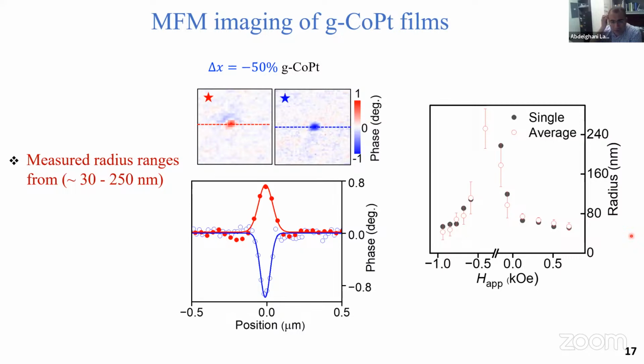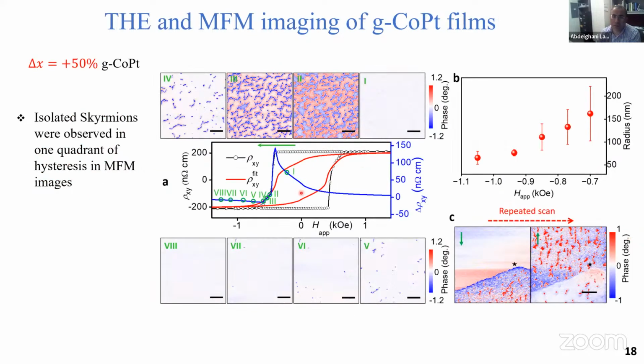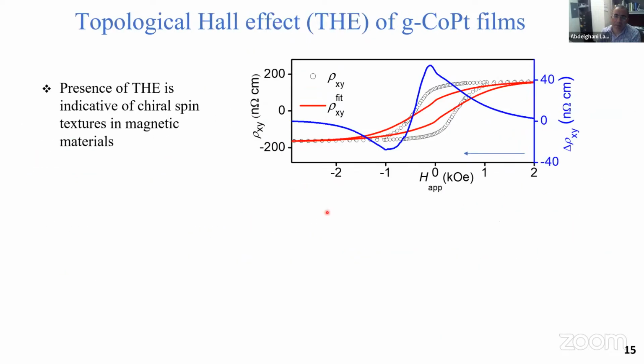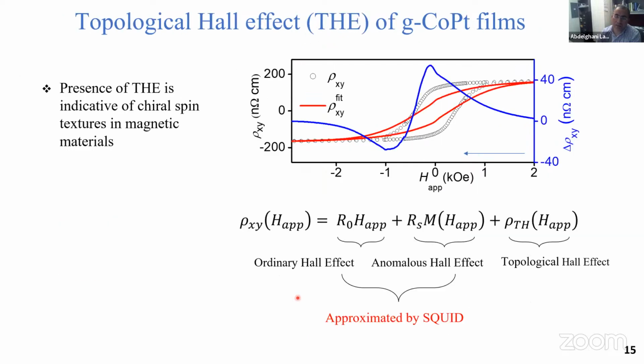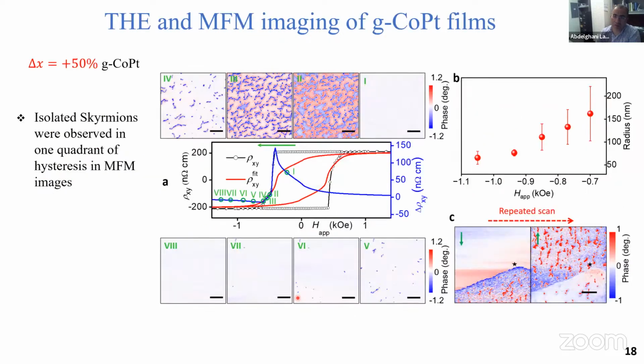We did a similar measurement on the positive sample. As I said, from the measurements, it has high PMA. When we do both VSM and topological Hall measurements, we see a very sharp topological Hall effect that is strong on one side and weak on the other side. Looking at the spin textures, it is first dominated by the formation of labyrinth domain structures, but if you go to lower fields, you can stabilize skyrmions, and then when you saturate, they disappear. Here again, we plot the radius.